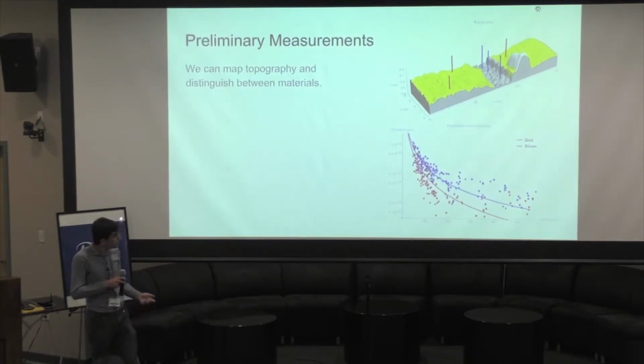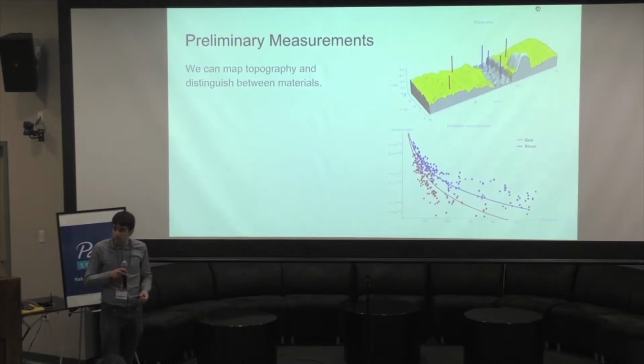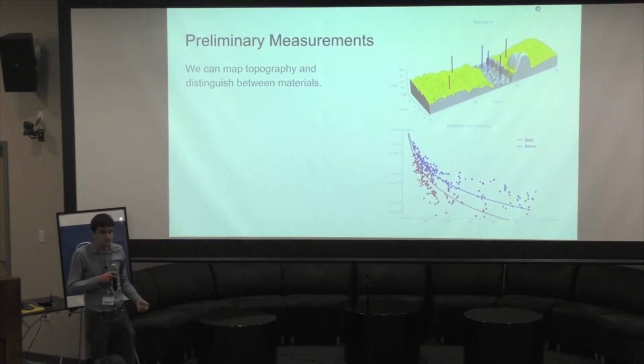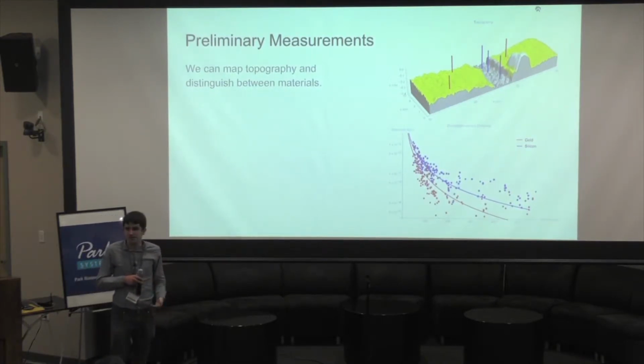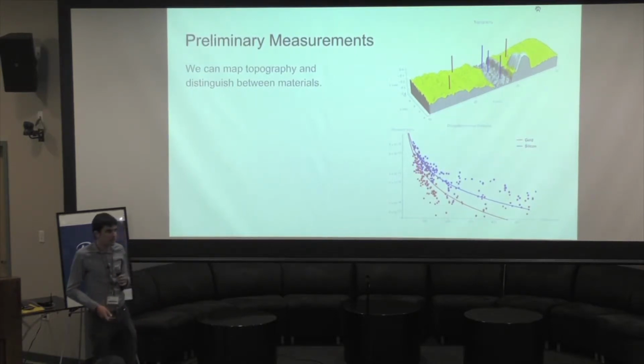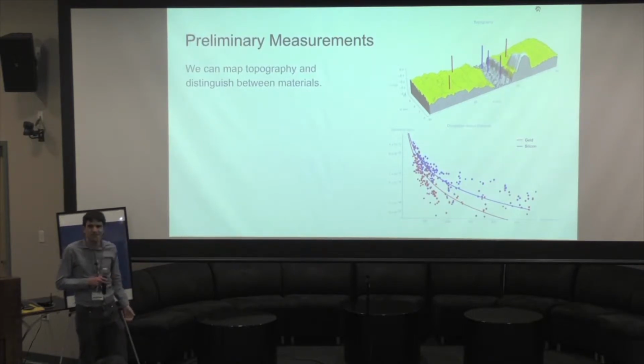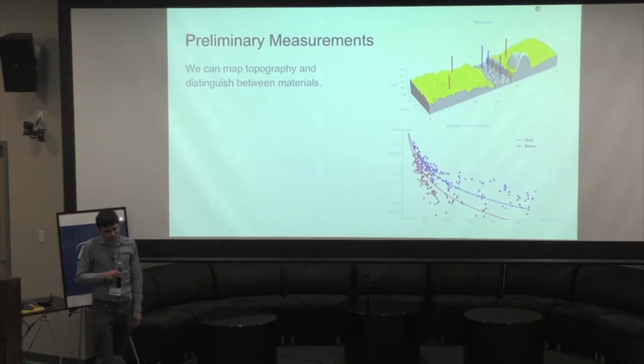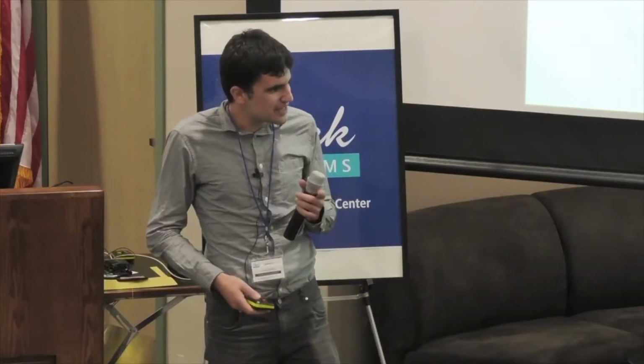Since then, we've made some improvements to the process, reducing the hysteresis from repeatedly moving up and down like we did in these measurements, and also automating selection of the parameters for the ring downs so that we can get good quality data with less measurement time. In the middle, though, we spent several weeks cleaning out some contamination in our vacuum system that resulted in substantial quality factor decay without any samples present. So that delayed the acquisition of the data I'm about to show you, some of which until about yesterday.